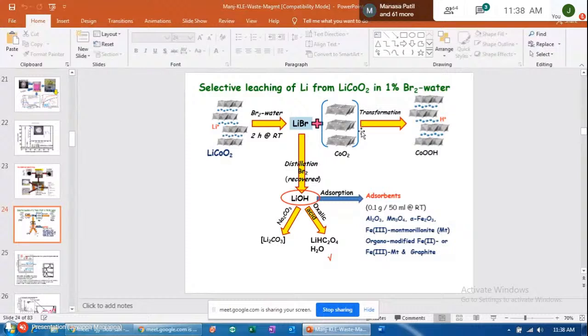Now, perfect, it is 100% removal, and the lithium bromide I can precipitate again. I distill it, so as I said, it's a closed loop. I can distill that bromine and collect it by cold trapping, and then again lithium hydroxide is formed, which can be easily precipitated as lithium carbonate.